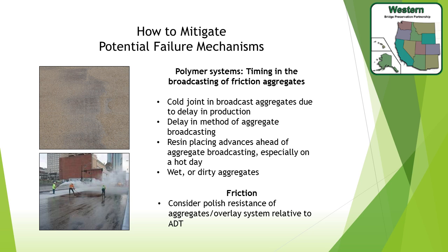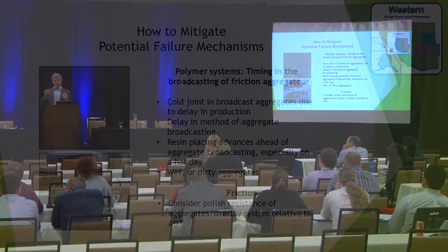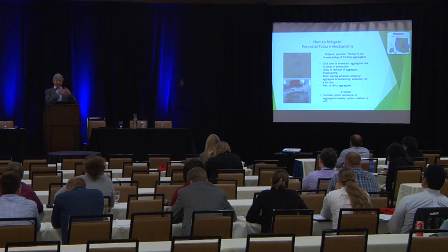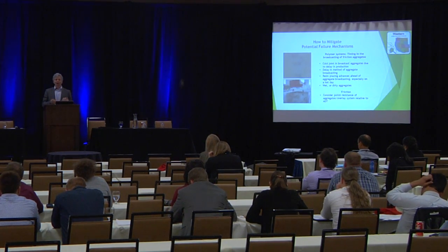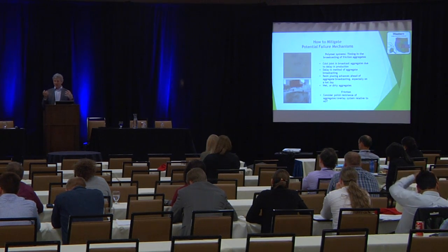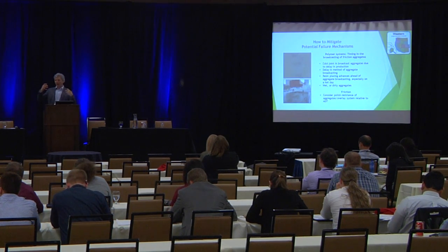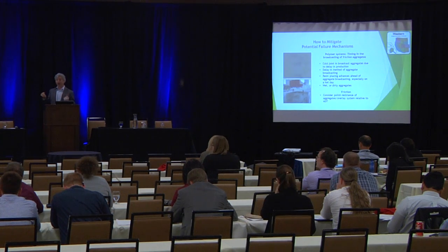That can happen more extensively with fully automated equipment. On a warm day it's very critical to embed the aggregate right away. Even if the resin binder doesn't physically seem like it's gelling, it's already cross-linking and gaining its strength. If you get the rock in a little bit too late, it's not integrated in the system — it's not cross-linking with the aggregate and bonding mechanically and chemically like it's supposed to.